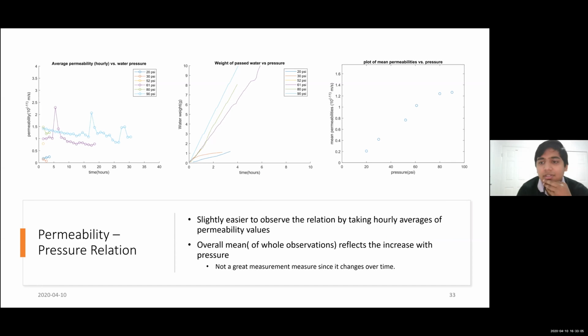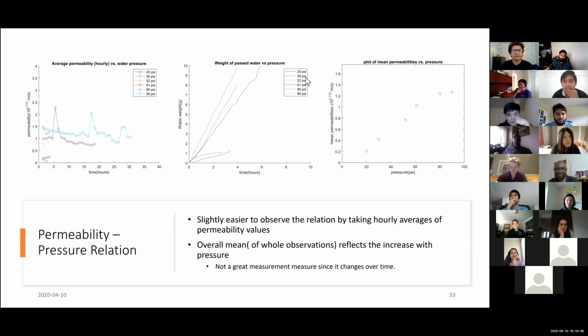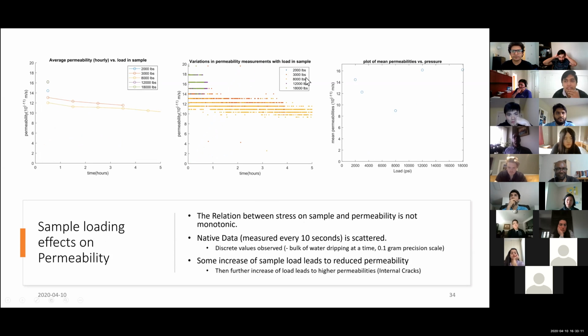I mean, in your curves. This one, I saw that. Show me which curve you're pointing at here. So in this one, the plot of mean permeabilities. Oh, I said it's pressure, it's actually load. So with increasing load, you have the mean permeability. Right. So when you convert that to stress in concrete, that's your load. Yeah, so this is around 10 MPa here. So that's approximately 30% of your compressive strength. Oh wow, that makes sense now. Okay, it's about 30%. You start to actually see an increased value of permeability.